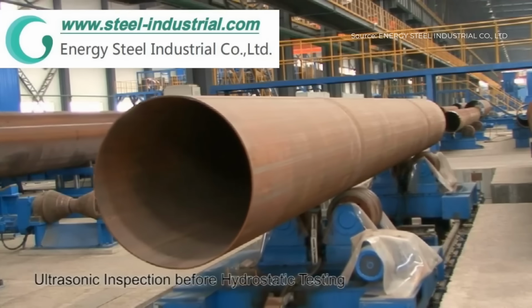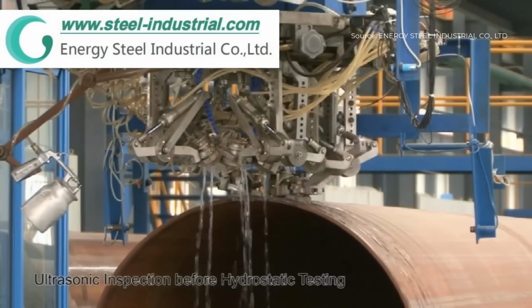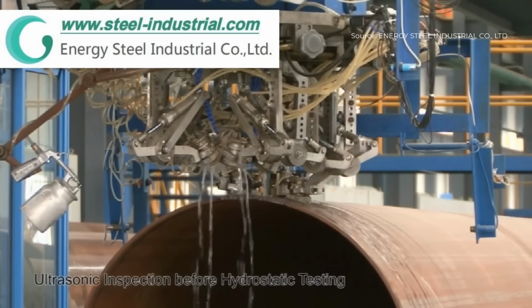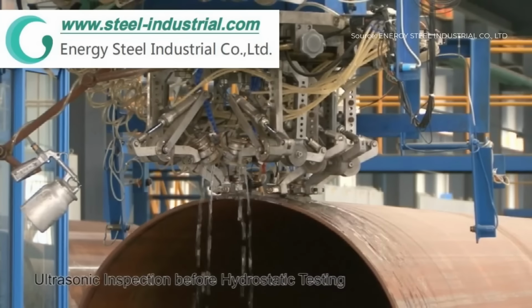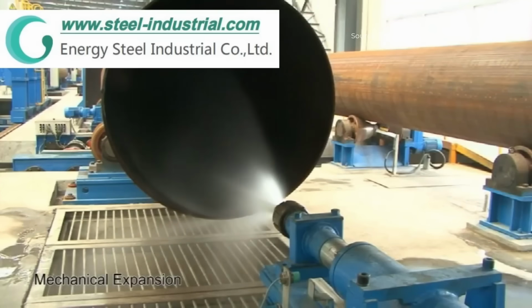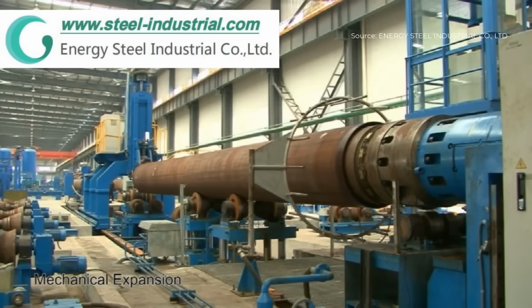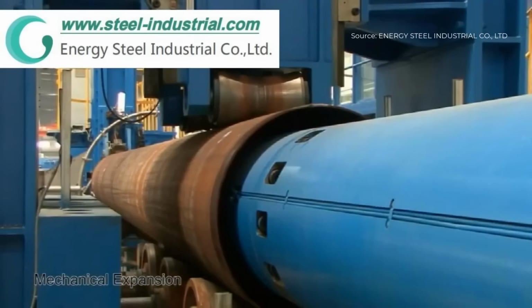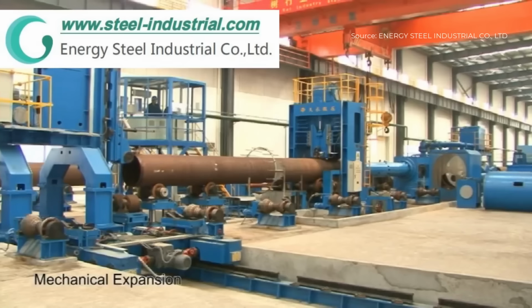Before hydrostatic testing, the weld seam is examined using ultrasonic inspection to detect any internal defects along its entire length. This is followed by industrial X-ray television inspection, which produces real-time images of the weld seam to identify possible imperfections. Mechanical expansion is then applied along the full pipe length to straighten, round, and improve dimensional accuracy, while optimizing internal stress distribution.